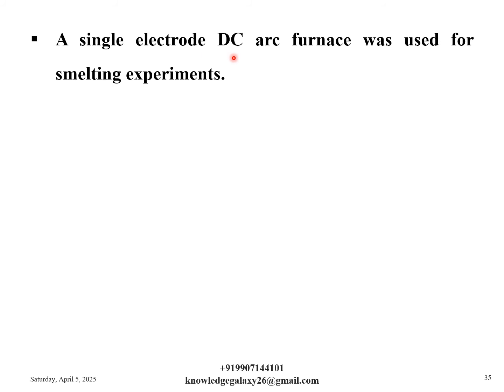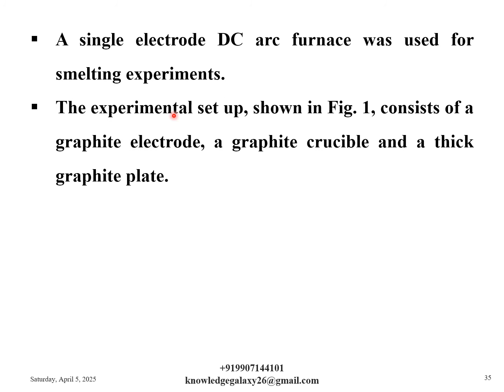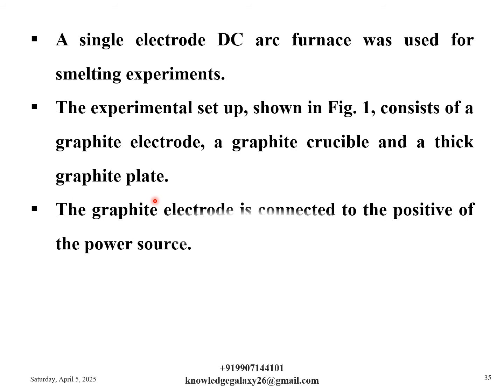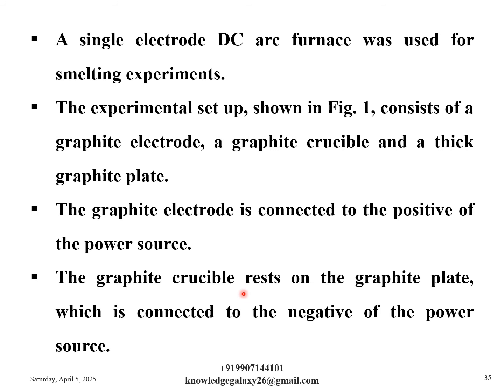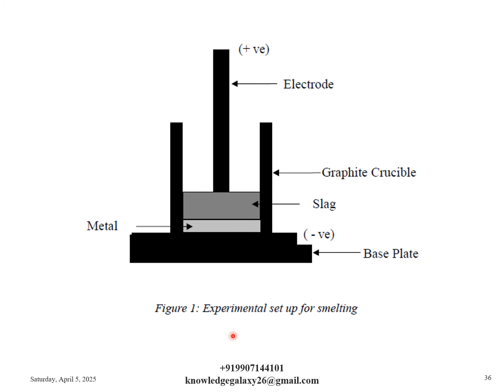A single electrode DC arc furnace was used for smelting experiments. The experimental setup is shown in the figure in the next slide. It consists of a graphite electrode, a graphite crucible and a thick graphite plate. The graphite electrode is connected to the positive of the power source. The graphite crucible rests on the graphite plate, which is connected to the negative of the power source. So this is the experimental setup for smelting, and I have just explained the details.